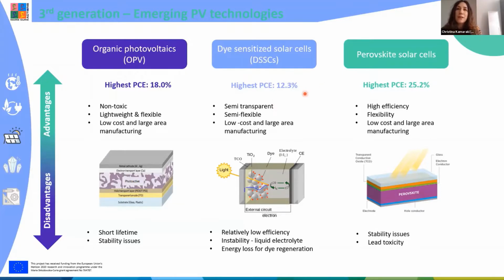And then we have the next big thing in solar technology, which is perovskite solar cells. They have been characterized as the fastest evolving solar cell technology since the efficiency jumped from 3.9% to 25.2% in only 10 years. Imagine that for silicon, it needed 40 years to reach 25%. So again, we can tune the bandgap, have flexible substrates, and use solution-based methods. But again, we have some stability issues and also the use of lead, which is considered toxic, is quite a controversial topic among the scientific and industrial community.